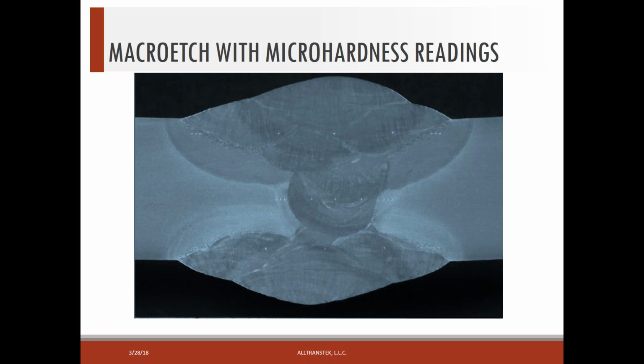Okay, this is a similar macro etch, but this is a double weld. It's not welded from one side, but again, you can see the multiple passes of the weld made from one side, and then multiple passes on the other side. And you can also see the little white indentations there, which are micro hardness tests in the weld metal and heat affected zone. So this is kind of what a macro etch would look like.